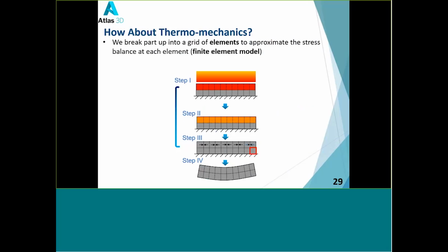So how about the thermo-mechanical process? How can we simplify this process and make it more efficient? The idea is that first we break the part into elements, and then we use finite elements to model the stress balance for each element. The second idea is that in the build process, the temperature profile is transient, changing all the time, but actually the stress accumulation is very slow. So you can solve the problem with the quasi-static method. You only need to look at a few temperature points in the build process.